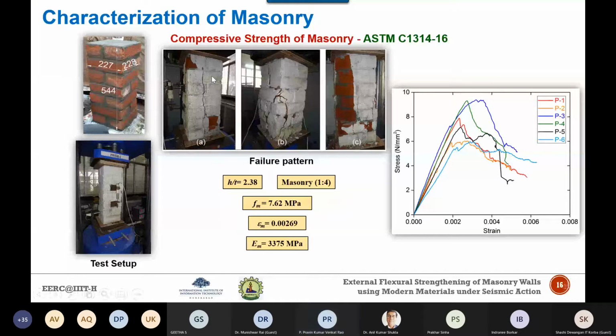Now, this ASTM standard classification identifies local variation in the crack patterns and spalling in the different tested specimens, which indicates that the material is not homogeneous. It is basically a heterogeneous material, and there is a large variability in the material properties, especially in the case of masonry. When we tested a masonry specimen with an H/T ratio of 2.38, we got a compressive strength of 7 MPa, and the modulus of elasticity is in the range of 3375.